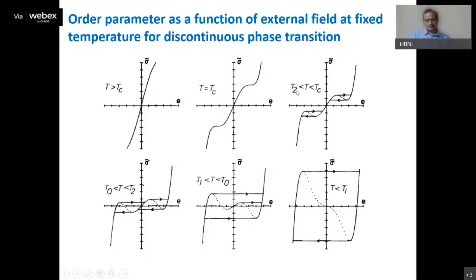Actually, these are the curves that describe the behavior of martensitic phase transitions. In the case of martensitic phase transitions, we describe the phase transition in terms of strain as an order parameter. So this sigma, the external field, is actually stress. So it is nothing but the stress strain curve describing the martensitic phase transitions, which take place by some coordinated movement of atoms, very small displacement. Actually, this is the case which is very relevant for high pressure phase transition, as we will discuss shortly.